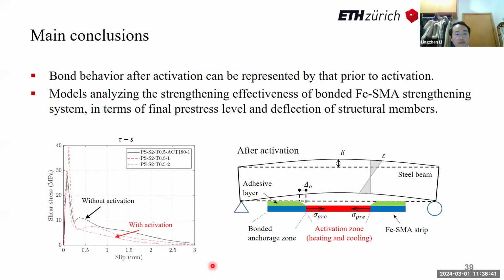measured force-displacement behavior. Afterwards, I analyzed the bond behavior after activation and found it can be represented by bond behavior without activation, even though at the very local mechanical level there is some difference. But for engineering application, the global force-displacement behavior, etc., the difference is negligible. In the end, I proposed a model and conducted tests to analyze the efficacy of the strengthening system. This model can predict the pre-stress level accurately, in terms of the compressive stress induced in the parent structure as well as the deformation of the substrate structure.